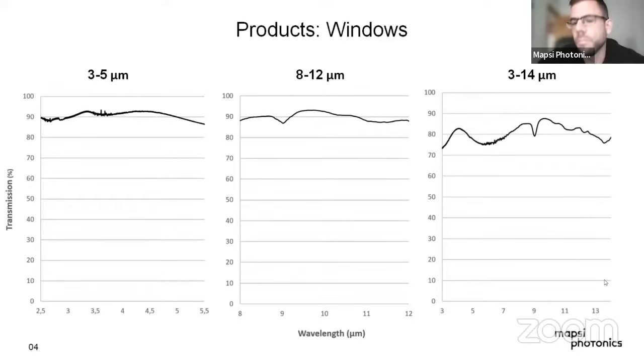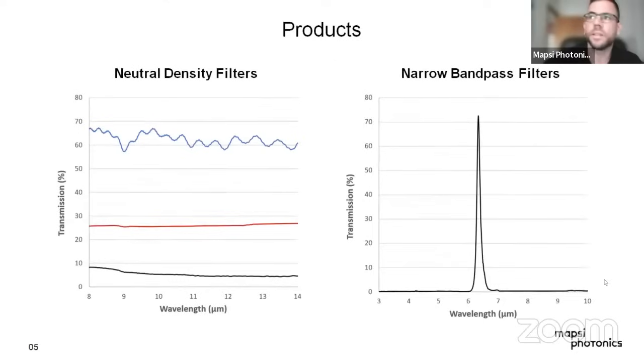We are above 70%. Many times we are much above 80%. And one of the things that is interesting for this is that, as I said, we don't use multi-layer filters, so we don't use anti-reflection layers, and we avoid the angle variation, which is something interesting also for our customers. And since we use only silicon, our filters can be really easily cleaned with alcohol, water, or wipes, for example. Other products that we have are neutral density filters that are used in thermal cameras just to reduce the amount of impinging light that is impacting the camera. We can manufacture, as I said, from 90 to 1% or 0.5% of transmission, really flat when we are in low transmissions. And also narrowband pass filters that are used in thermal cameras as well as in gas sensing.